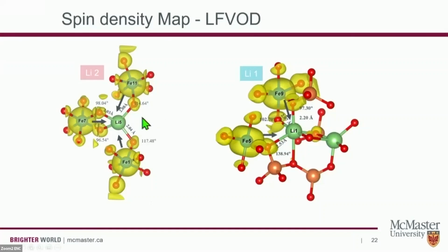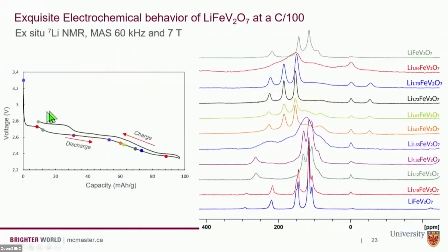And so we went forward from here to then think about the structure and how it changes during the electrochemical process. So this is the electrochemical curve that I showed you. We've taken a spectrum at each of these data points going along. And the really significant change happens here at lithium 1.55, where everything broadens. And then all of a sudden, we have a new set of 3 peaks. And we had this data actually quite early on. Before we had done any of the structural investigation, we had this evidence of NMR telling us there's a phase change happening here, and there's a new kind of dynamics going on once we pass that phase change.